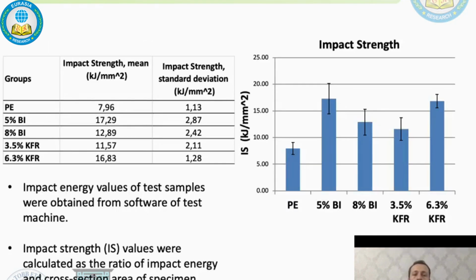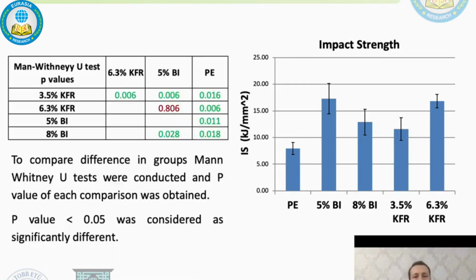Test results. Impact energy values of the test samples were obtained from the test machine software. Then impact strength values were calculated as the ratio of impact energy and cross-section area of the specimen. The mean and standard deviation values are calculated and can be seen as a table on the left side and as a graph on the right side. To compare differences between groups, Mann-Whitney U-tests were conducted and p-values of the pairwise comparisons were obtained. A p-value below 0.05 was considered significantly different.